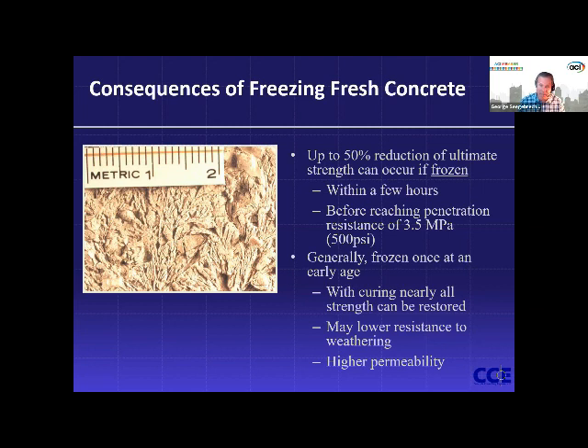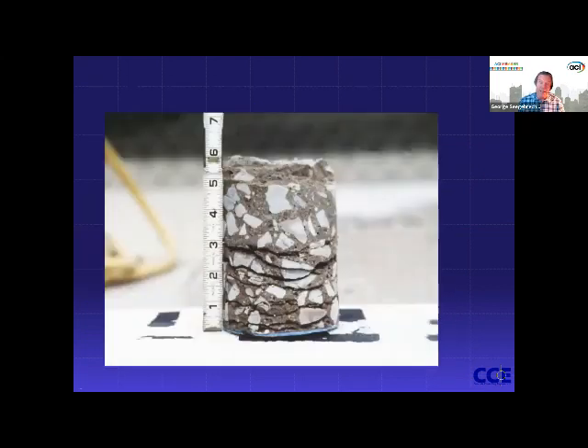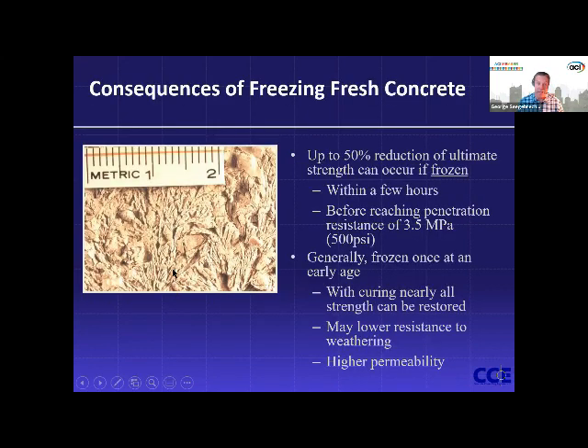It might just have to be milled off. On that job where I said the casino in the Midwest had the protection blow off, it was very superficial. It looked bad, but once we got a core and saw how deep it was, and most casinos have carpeting over their surfaces, it was not as big of a deal for them once we removed this. So when we say 50% reduction, it's just what's frozen that did not reach the 500 psi penetration resistance early on. That is freeze-thaw damage, not to be confused with freezing of paste.